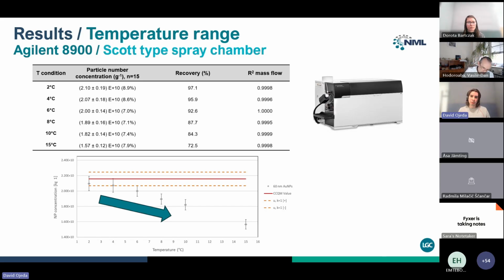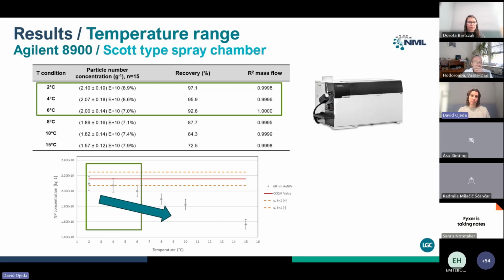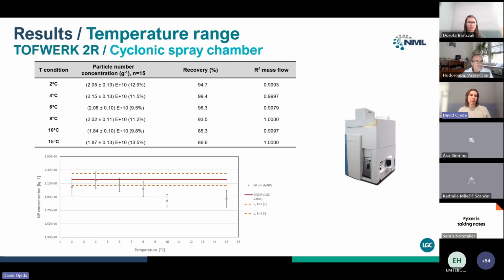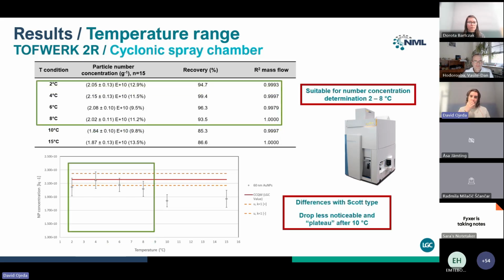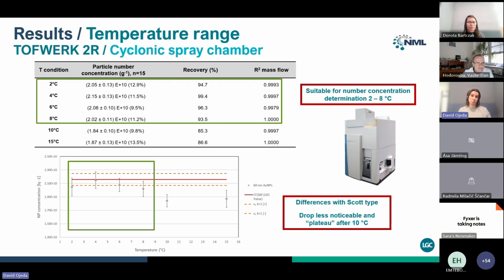Considering the graph at the bottom of the slide with the CCQM value in red and the dashed lines as the uncertainties with a coverage factor of 1, we can determine that the results obtained from 2 degrees up to 6 degrees were still within the uncertainty, so it is still suitable for accurate number concentration determination with the DMF. That's what we saw with the Agilent 8900, but when we used the TOFWERK instrumentation with a cyclonic spray chamber, the results were a bit different. We can see a plateau that extended from 2 degrees up to 8 degrees, in which we were still obtaining a suitable number concentration determination by the DMF.